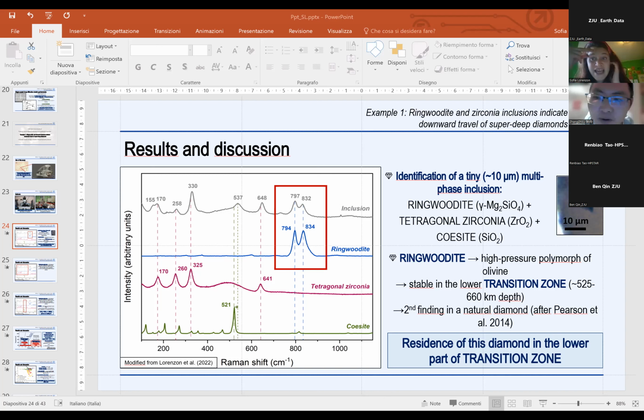This inclusion is under residual pressure, but for this particular case of multi-phase inclusions, we must consider too many parameters, and the combination of these parameters probably doesn't allow us to obtain real results about the internal pressure. Also, we don't know if there is a crack around the inclusion, because a crack leads to a loss of the residual pressure. Considering the amount of inclusions within this diamond and its extremely big size, to understand this we must perform micro X-ray tomography.